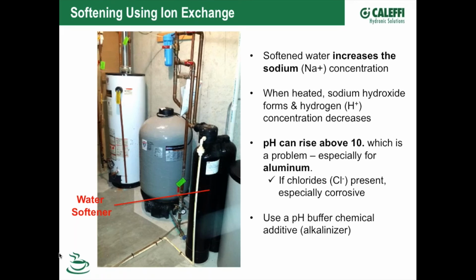It does do a great job preventing water from scaling. It can prevent scaling to a very large degree, if not completely eliminate it. But you've got the issue of this potential corrosion issue. Some people say it's the lesser of two evils. If you've got water where the hardness is off the scale, like many places in the U.S. now, are you better to use the softened water than putting in water that might be 100 grains hard or something like that? Well, just know that you're substituting one lesser problem for another problem.